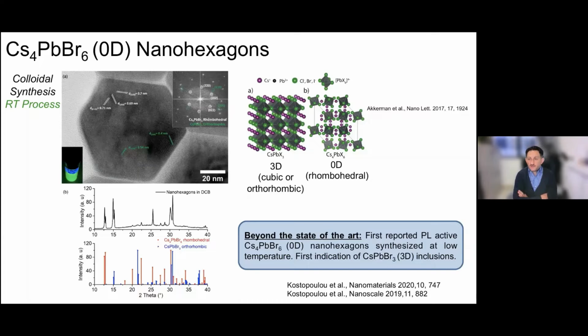So the first system we have worked on is by Nancy Kostopoulou, a postdoc in my lab, who has worked in this direction. She has produced zero-dimensional nanohexagons through colloidal synthesis, in a room temperature process. This is very nice about the formation of these nanohexagons: they can be easily formed at room temperature. This is the structure you can see here. There are some inclusions of the three-dimensional phase in these zero-dimensional nanocrystals, as you can see in this TEM image and also in the X-ray diffraction measurements.